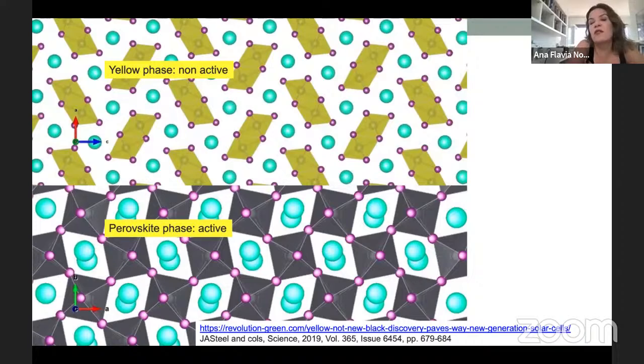Because they are non-active. If you compare the structure of the two phases, the cubic phase and the hexagonal phase, you can see here that the octahedra in the yellow phase are not connected to each other. It means that they are absorbing in a condition where there is a high band gap semiconductor. So this is not interesting because you're not absorbing most of the visible or the infrared. And also in terms of transport, the mobility here is pretty low, okay? So we don't want these yellow phases.